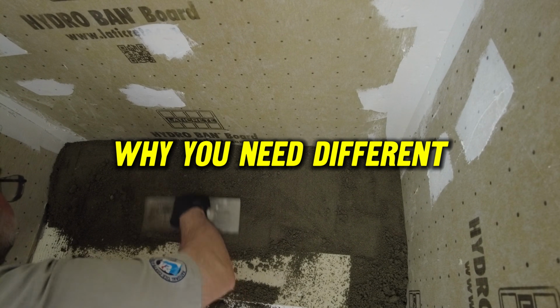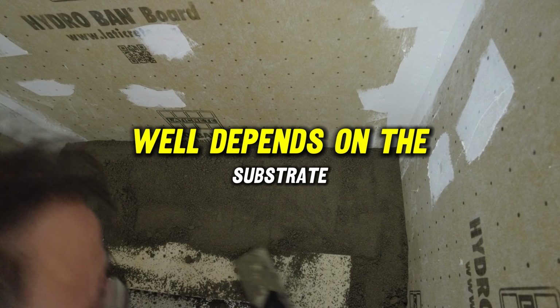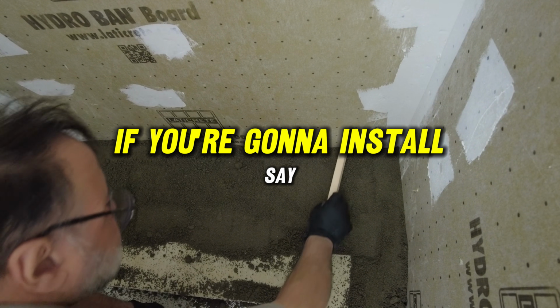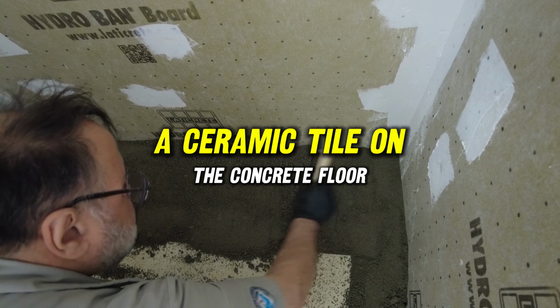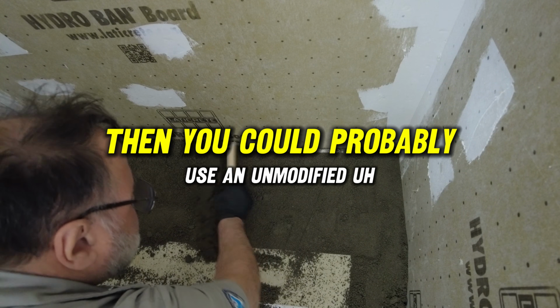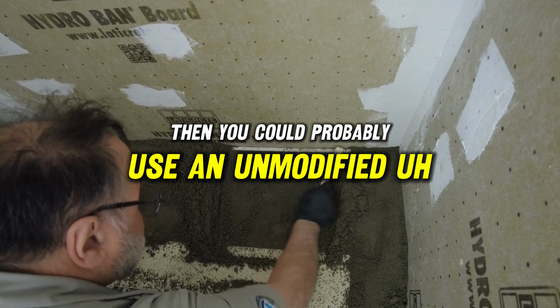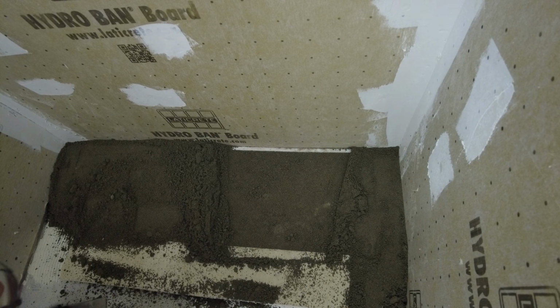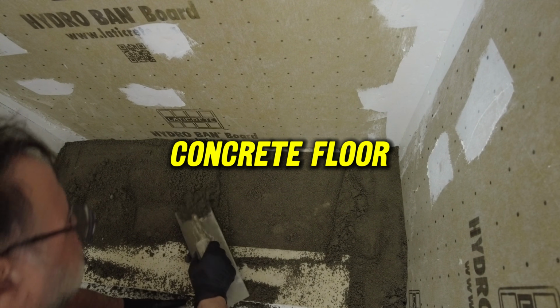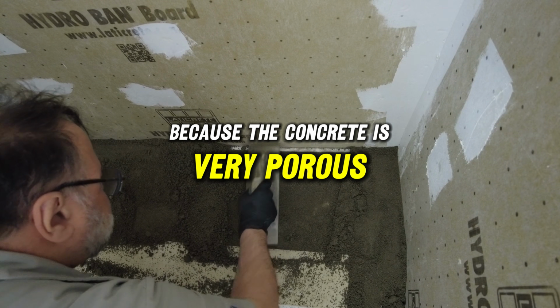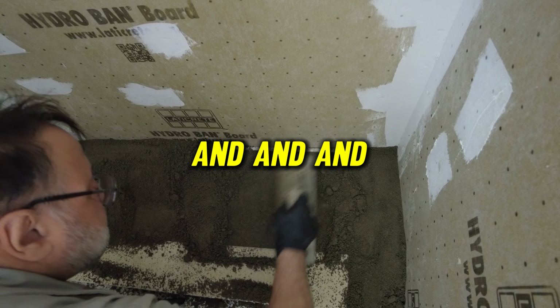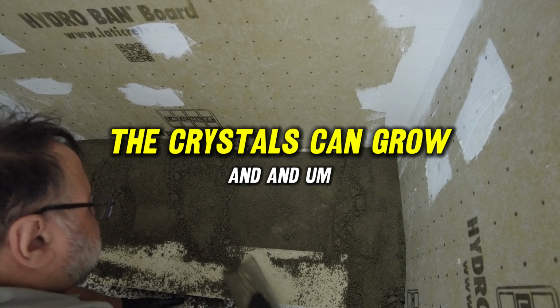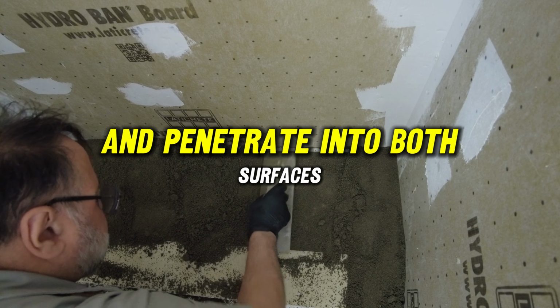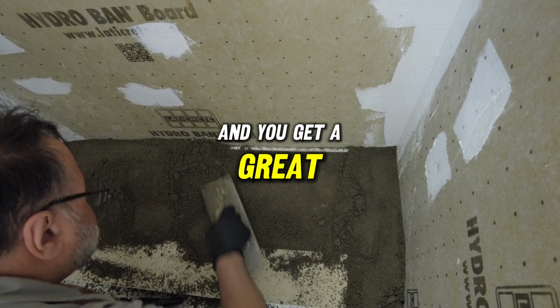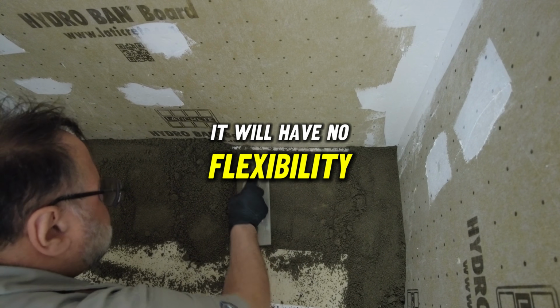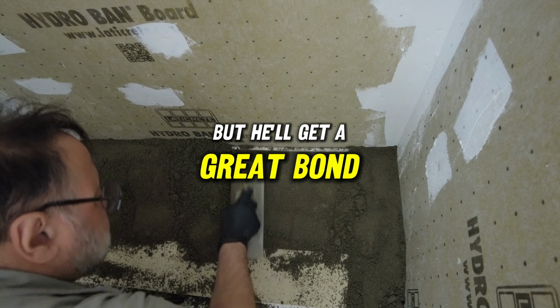Why do you need different thinsets anyway? Well, it depends on the substrate you're going over. If you're going to install, say, a ceramic tile on a concrete floor, then you could probably use an unmodified thinset directly on the concrete floor, and it'll stick to both, because the concrete's very porous, the ceramic tile is porous, and the crystals can grow and penetrate into both surfaces, and you get a great bond. It will have no flexibility, but you'll get a great bond.